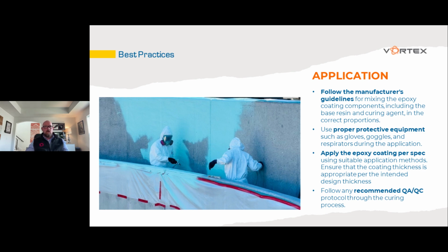We're also very heavy on, and everybody on this call should be, safety first. When we're talking about these materials and installing them, everyone needs to be protected from any inherent dangers there may be. So protective gloves, goggles, respirators and those types of systems are absolutely key as well. And then we apply the epoxy per spec. Usually the specification on a manhole doesn't get above 125 mils, but it can, and if so, then we can build up to 250 mils.